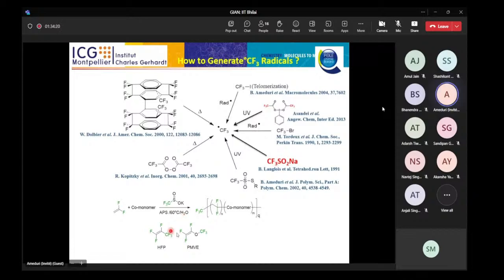So the idea was to use a system which enables us to release some CF3 in order to have a CF3 end group and then a polymeric chain, so that the CF3 end group by NMR was possible to give information about the molecular weight. So we did homopolymerization of VDF, but also copolymerization of VDF and HFP, and even terpolymerization of VDF, HFP, and perfluoromethyl vinyl ether. Under these conditions, we need an oxidant in order to release the CF3 radical.